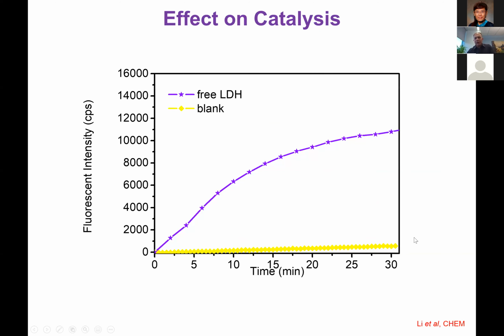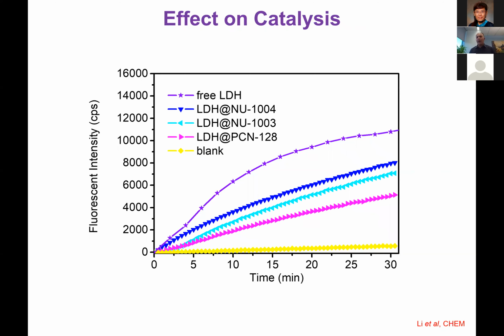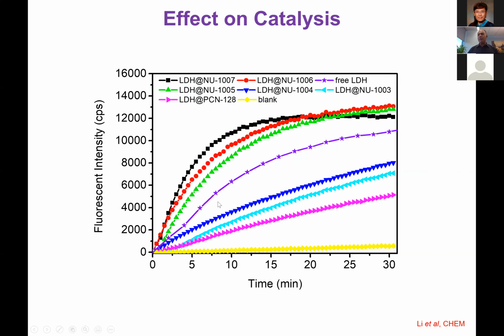Here, what I'm showing you is the blank without the catalyst, which is the enzyme, and here, everything in solution. This is the homogeneous. If you take our 3 smallest MOFs, they are not as good as the free enzyme. If you remove the diffusion and make large channels and have now both the substrate and the coenzyme diffuse, we get materials that are more stable, but beside that, they are more reactive than the free enzyme as well. So that's nice.